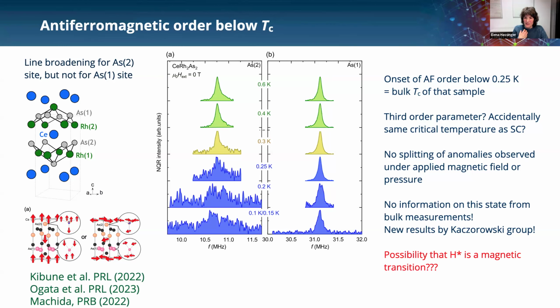Now the question is, is there a third order parameter, so the T0 order, superconductivity, and antiferromagnetism? In bulk measurements, we only see two transition temperatures. So is that because two of the three order parameters accidentally have the same critical temperature? These are open questions. What I can say from our measurements is that we don't see a splitting of any anomalies when we apply magnetic field or pressure. So we do not have any information on this state from our bulk measurements. That's why I'm not going to say anything about it from now on.